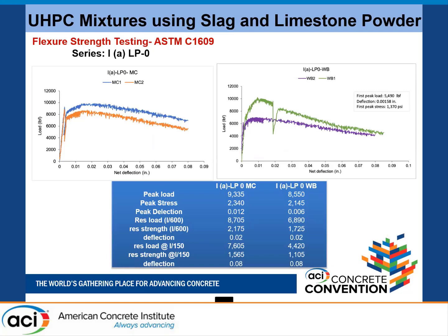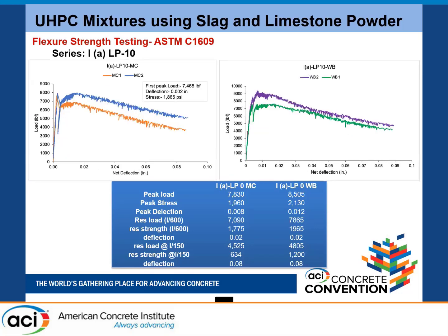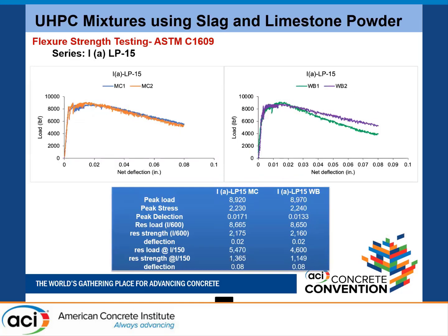We got the peak stress here of 2,145 psi. That is the modulus of rupture value or flexural strength of this concrete with no limestone powder. This is 10% limestone powder, similar, approximately 2,130 psi flexural strength with 10% replacement of cement with limestone. And this is 15% limestone, 2,240 psi. And the residual strength is great, at approximately 50 to 60% residual flexural strength we can get even using 15% of limestone replacement in combination with slag. That is a great finding.